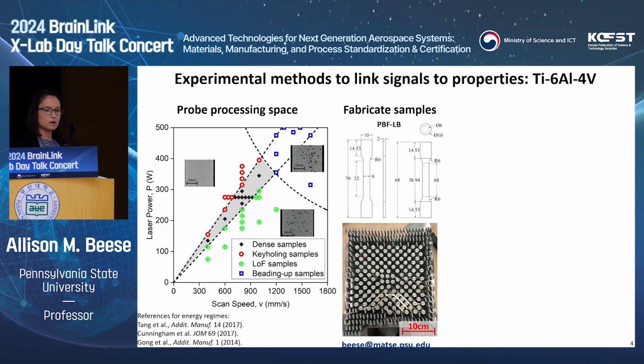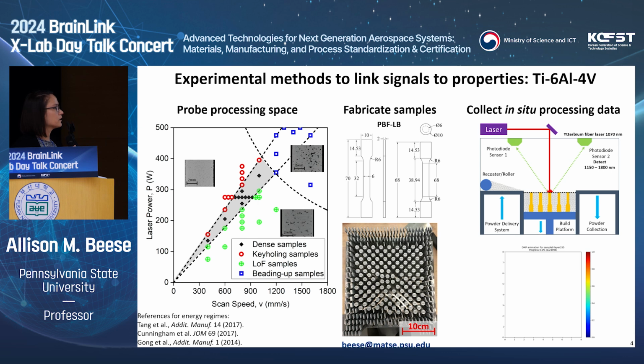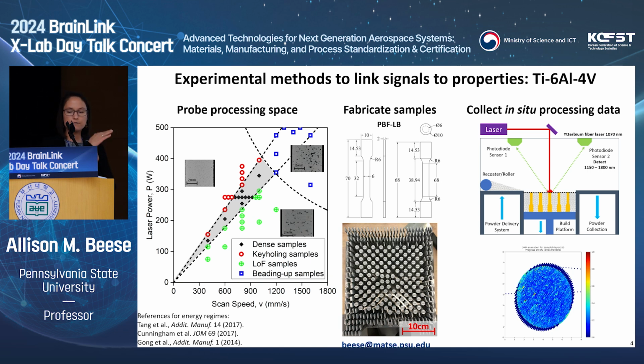So we fabricated samples with each of these, looking down at a build plate. Each of these tensile samples has a different power and scan speed combination. And in particular, what we're doing is we're monitoring the process during fabrication. So we have photodiode sensors in our build chamber, and we can monitor the intensity of the photodiode at every point in time, as shown by this video here, where the photodiode intensity is shown by the color, and this is scanning a single cross-section of one of those round tensile bars. So what we do is we have then data during processing where we have information of the photodiode intensity of each of those approximately 300 samples, 500 layers of data, and we can use this and we want to say, are there particular signatures in that image that tell us that we're processing something with a low strength or a high strength or ductility?